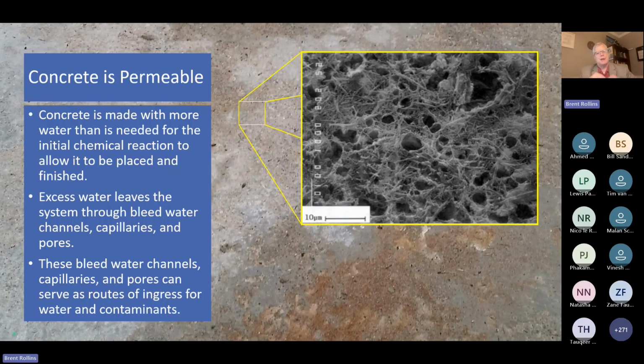And when it's placed, some of that water that is in there to allow us to place that concrete leaves through bleed water channels and capillary void structure. So you have some evaporation of that extra water, that water of convenience that we use to help place concrete. Some of it leaves during the setting process.